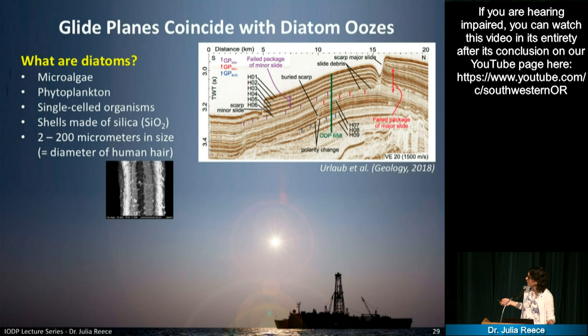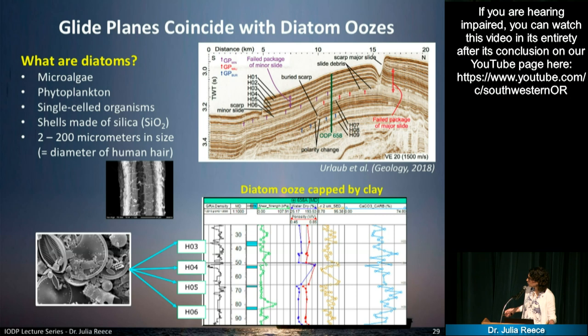So we have a few of these layers. I show a zoom in from a few of these layers indicated in the turquoise color. And if we look at their properties, these layers that are so rich in these microfossils have extremely high porosities, low densities, and therefore there's a significant change in the properties to the overlying and the underlying material. And especially if you cap these layers that are extremely rich in microfossils and water with a material that's clay, for example, that has almost no ability to drain this water that's in the microfossil, then you can build up a pore pressure, a high pressure in these sediments, and that could then potentially destabilize the sediments on the continental slope.